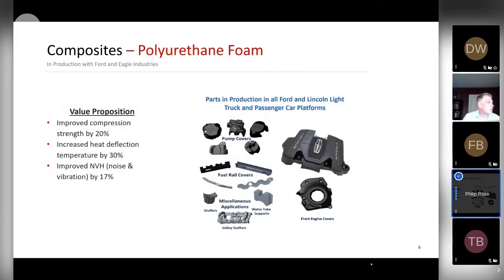Fast forward to today, and Ford is in production with our graphene nanoplatelets to enhance the performance of under-the-hood molded polyurethane foam parts, and they've published performance improvements that include 20% improvement in compression strength, a 30% improvement in heat deflection temperature, and a 17% improvement in noise and vibration isolation.